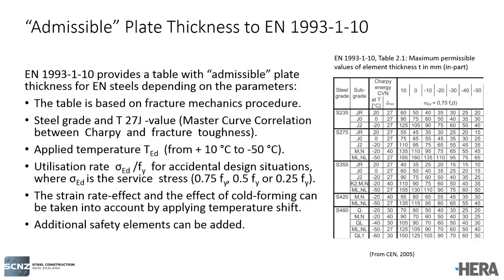And some of the parameters considered in this table are tensile and notch toughness values of the steel, properties of the steel, lowest air temperature for that application, utilization rate. It means the actual service load as a percentage of yield strength of the steel. It can be 0.75, 0.5, or 0.25 FY. The strain rate effect, for example, by accidental impact loading. The effect of cold forming can be considered. And additional safety factor can also be considered as a temperature shift. Next slide, please.